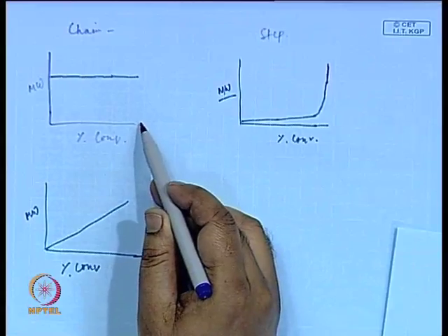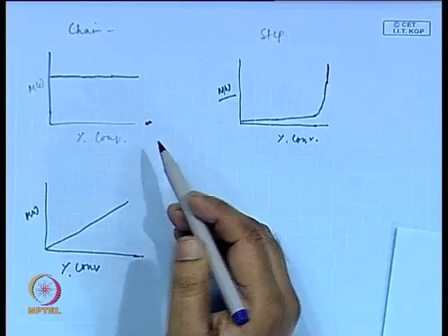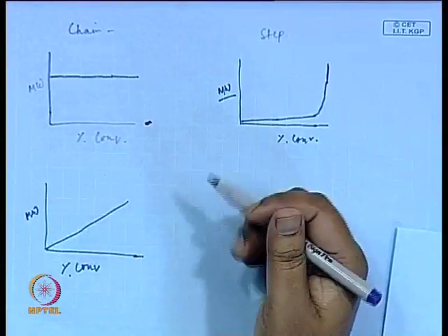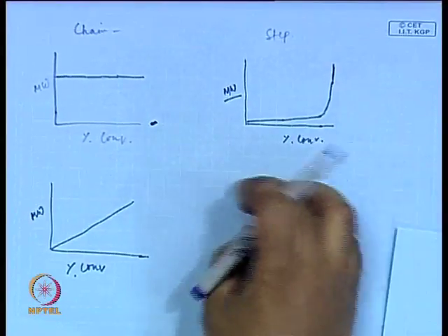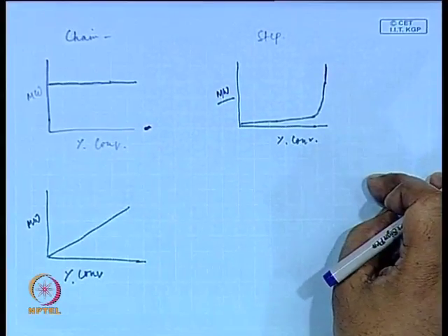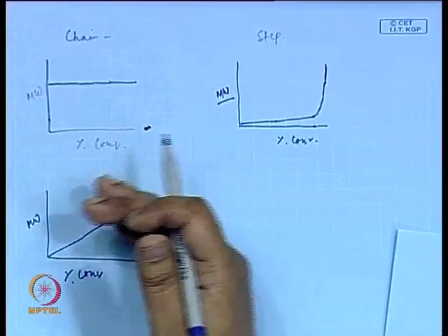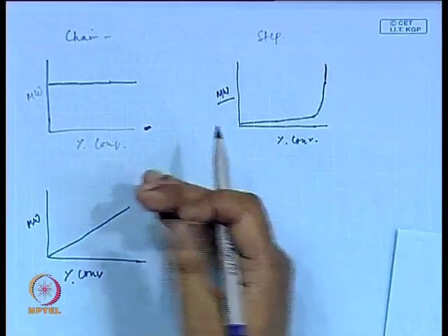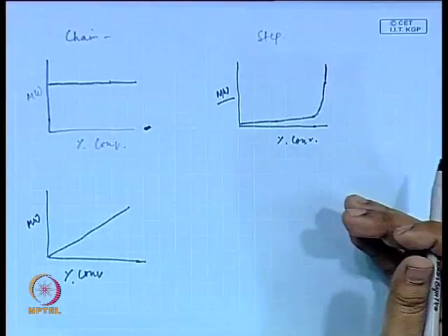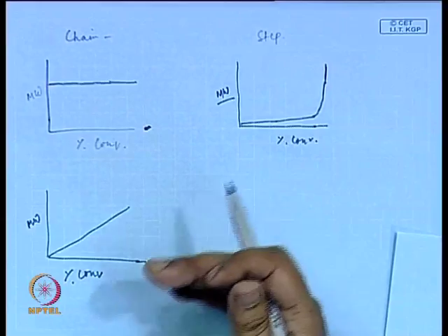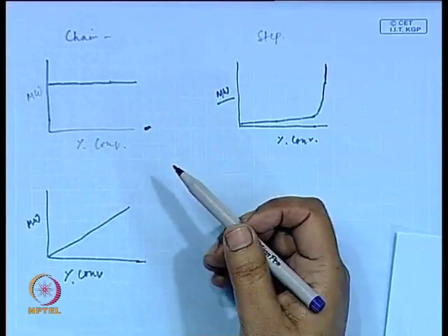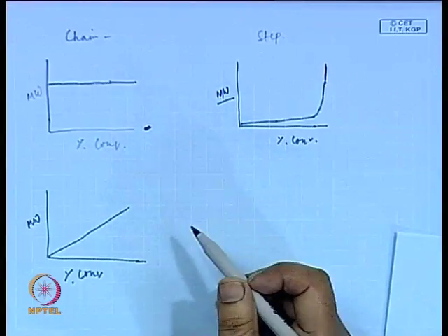So, in the first case, which is the normal, in general chain reaction, initiation is slower compared to the chain propagation, or the formation of the polymer chain, which means as the chain gets initiated, it completes very fast. So, you get high molecular weight polymer at the beginning, and as time goes, more and more chains get initiated. So, you get more and more polymer with the average molecular weight remaining the same.